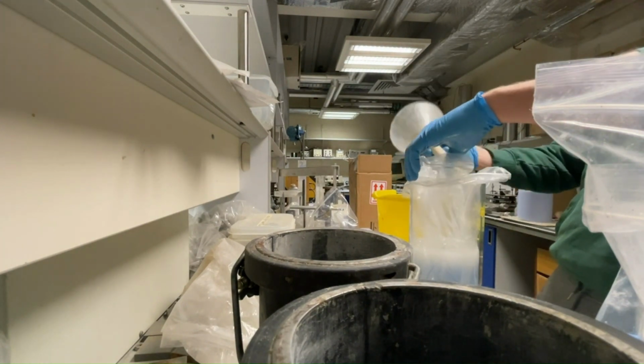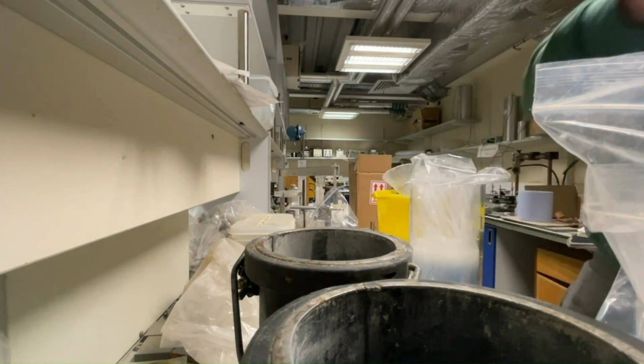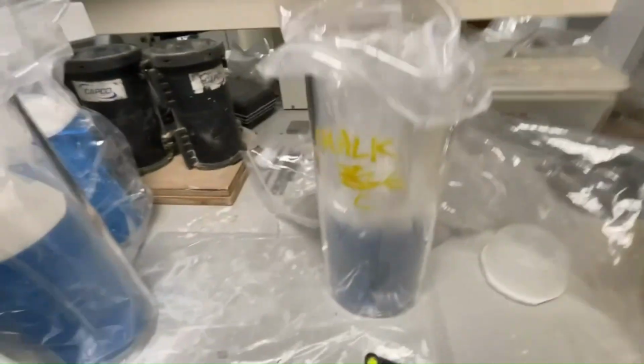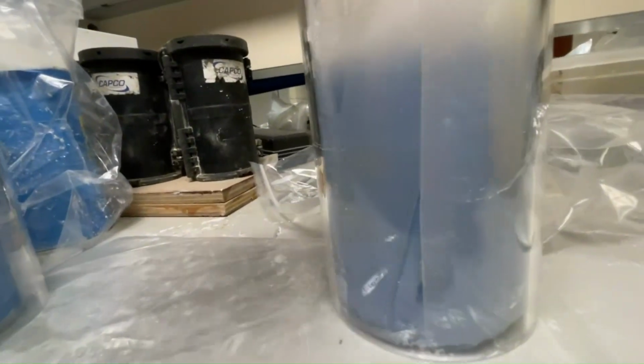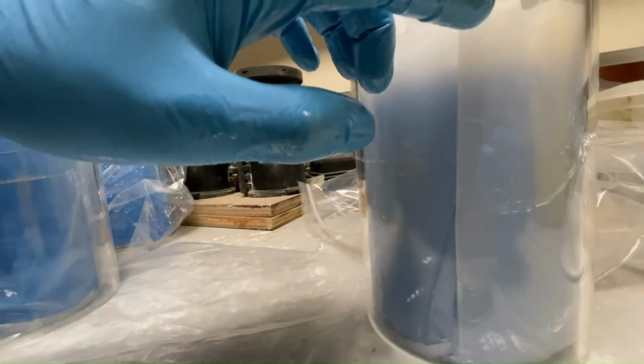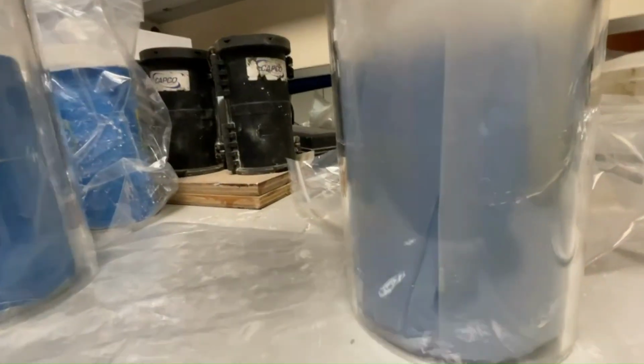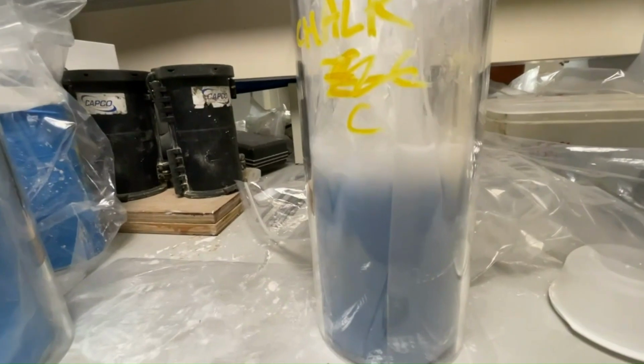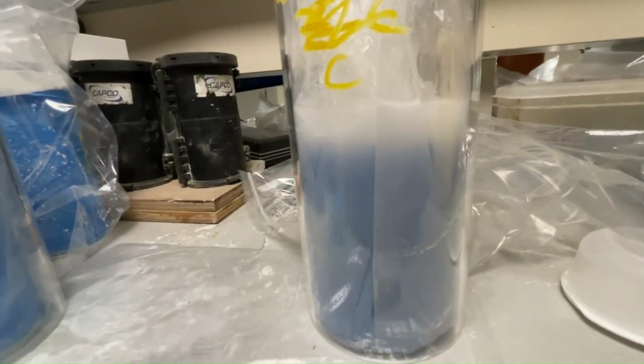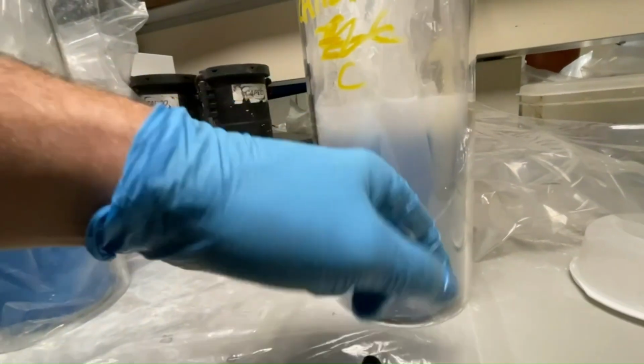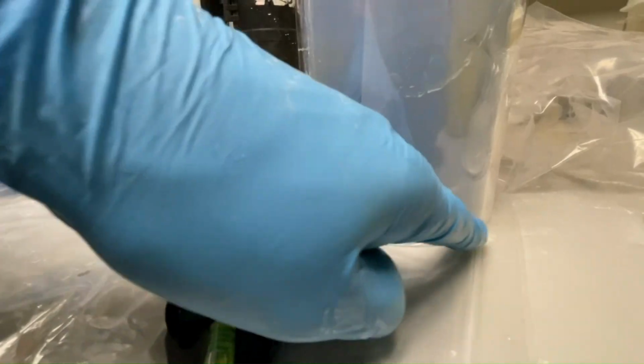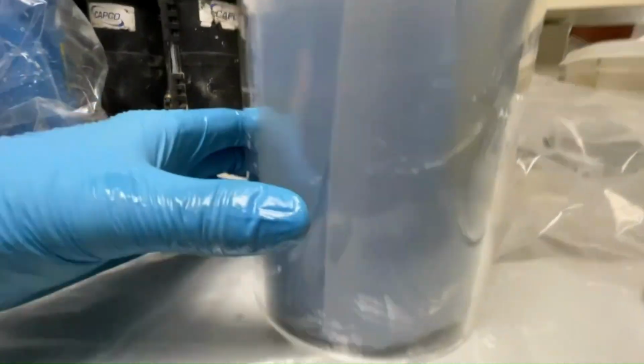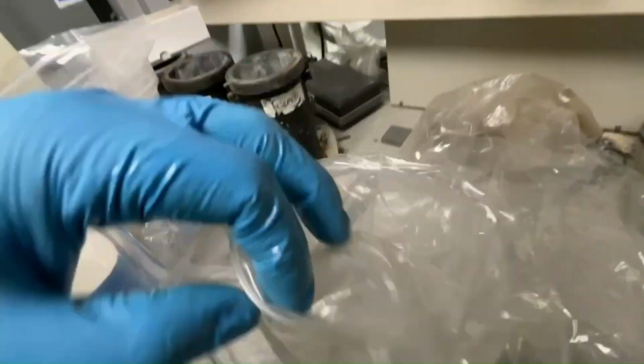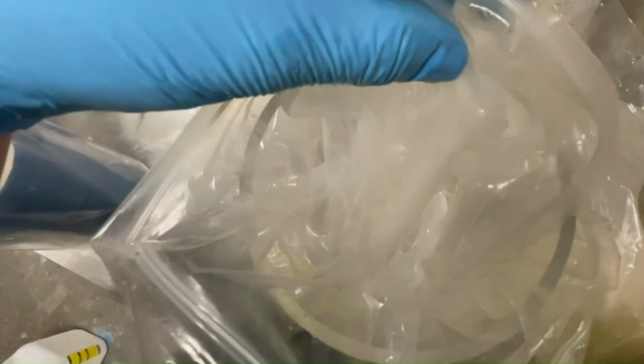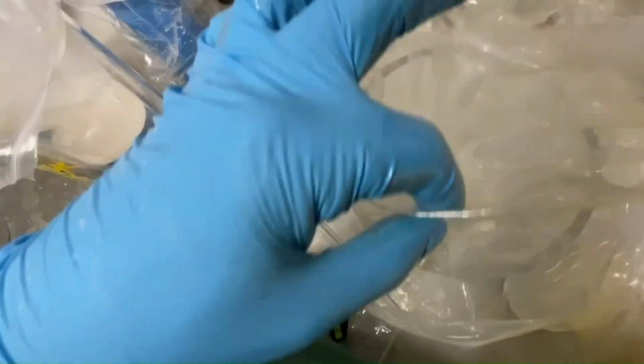So I'm pretty happy with this one. I'll just show you now. So you can see the epoxy is slightly above the sample. It will move down ever so slightly. There's not a lot of volume change or settlement as this resin cures. However, just with the bag, if I go back in and move these small recesses here outwards, they're obviously going to take some of the volume of the resin. So otherwise the sample's good. You can see it's nice and centered. It was also nice and level.